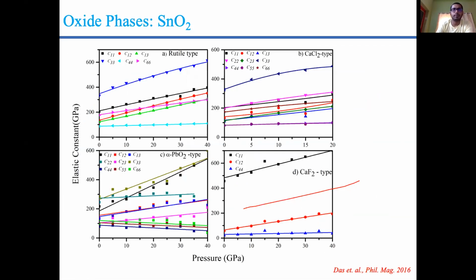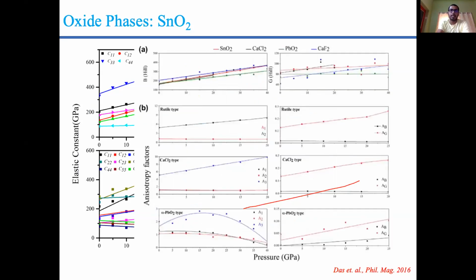From this sequential phase transition, we can say that these transitions are purely shear driven, as the pressure derivative of the shear modulus is nearly unity or negative. The elastic constants allow us to look into the directional anisotropy of these tetragonal and orthorhombic phases. As the rutile type is tetragonal, in the crystal structure two axes are the same, that is A and B, and C is different.